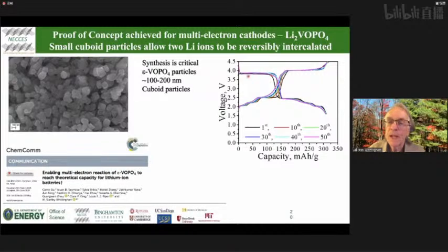So we have a flat plateau here, vanadium 5 to vanadium 4, then here vanadium 4 to vanadium 3. And you can see a series of bumps here. This is as the lithium is tending to order in the lattice. But the key thing to note here, the black curves is the first cycle, the purple curves are the 50th cycle. It's in fact better on the 50th cycle than the first cycle. So we got proof of concept that we can intercalate 2 lithium ions into a lattice without destroying that lattice. And we've done the same thing for sodium. So we now know we can do that.